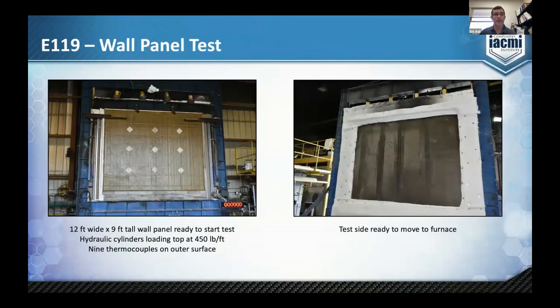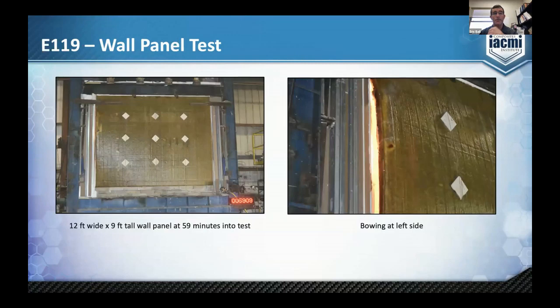So here's a wall panel test. It's 12 feet wide, 9 foot tall. It's hydraulically loaded to the top at 450 pounds per foot. And on the right there, that's the inside that's going to be exposed to the furnace. Here's 59 minutes into the test. You can see it's bowing on the right-hand picture. It's bowing quite a bit, but it's still maintaining that 450-pound load.